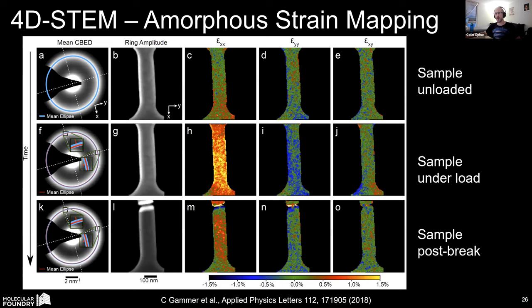And this was a very interesting observation that we weren't expecting. After you break, you actually have about a third of the total strain left over as residual. And so this is sort of the equivalent of plastic flow, but in a bulk metallic glass. The pulling on this material, the sort of deformation of it, has caused irreversible changes in the nearest neighbor spacing and next nearest neighbor shell spacing, which is sort of what we're picking up here in these materials.